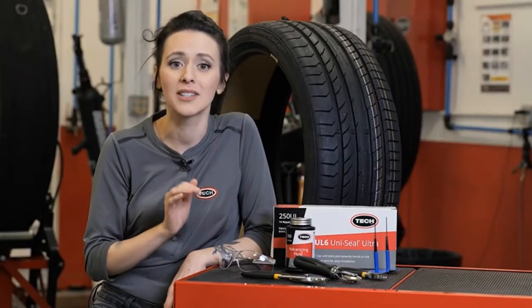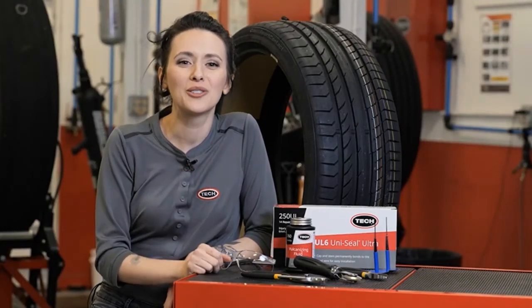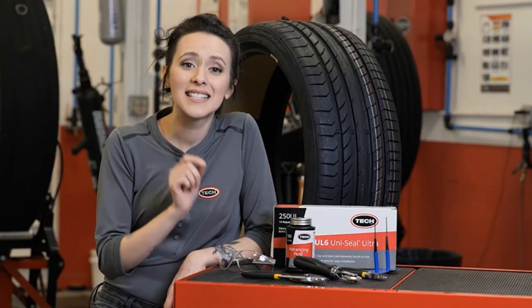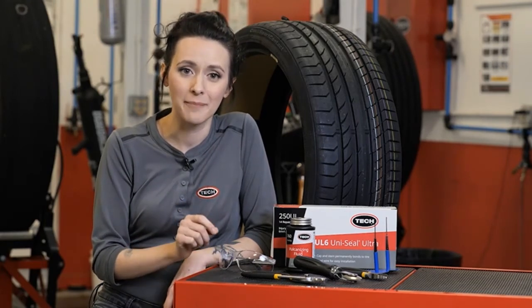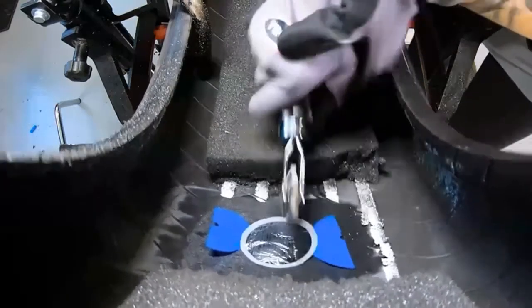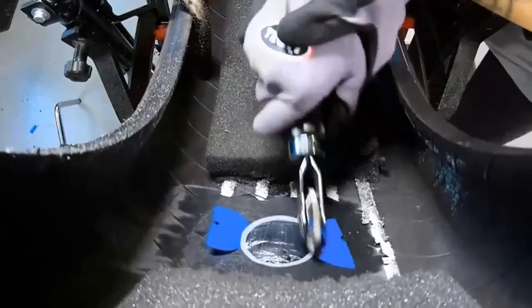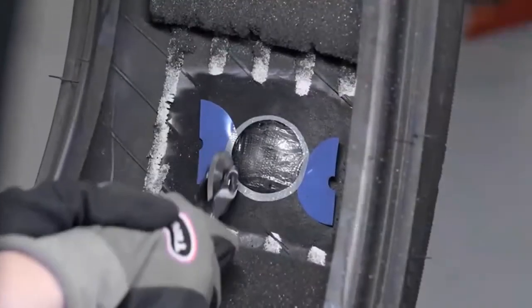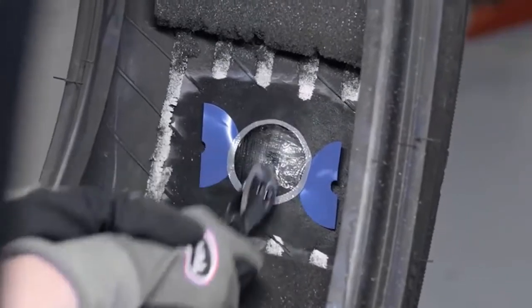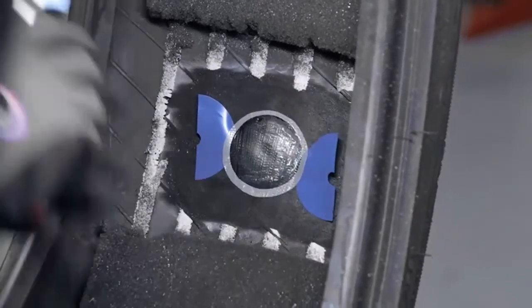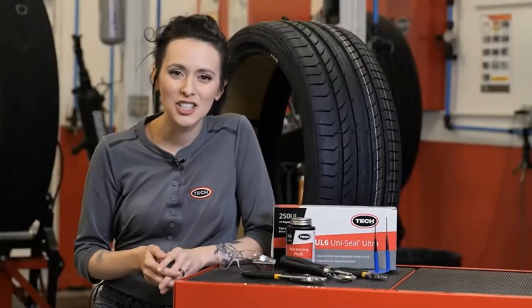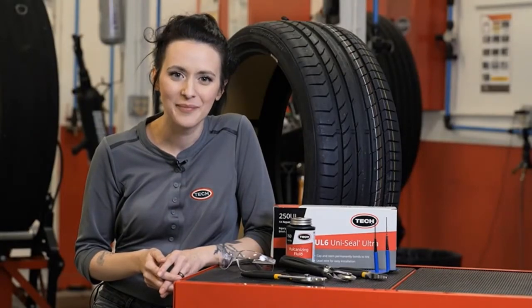Next, grasp the lead wire on the outside of the tire with a pair of pliers and carefully begin to pull the Uniseal Ultra into the injury. Pull until the repair unit seats against the inner liner. Be sure not to overpull. This will cause dimpling and possible breakage of the stem. Once the Uniseal Ultra is in place, press down on the center of the repair unit with your thumb.